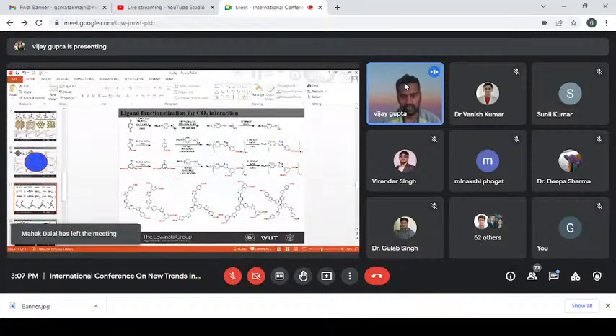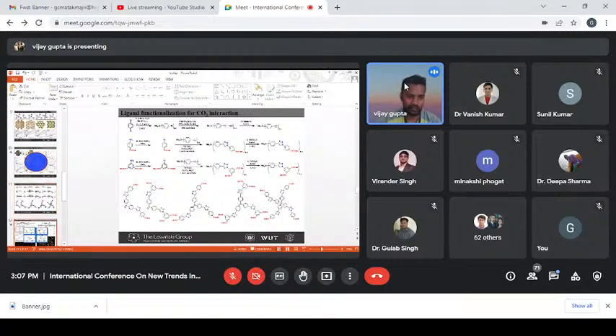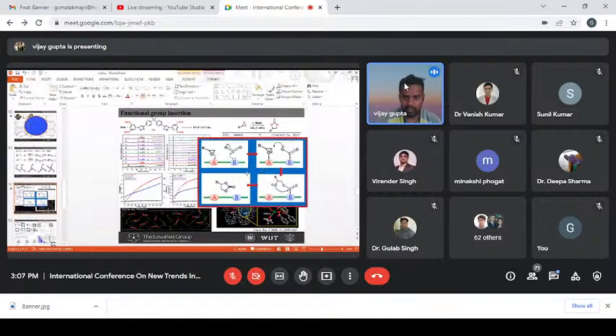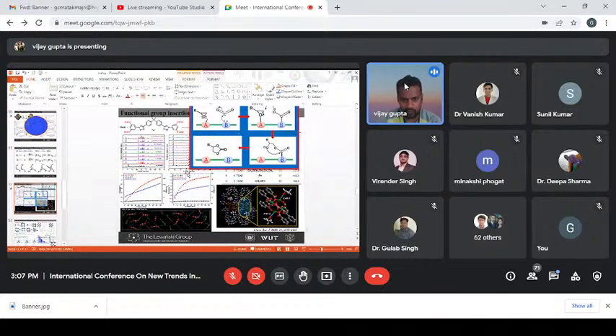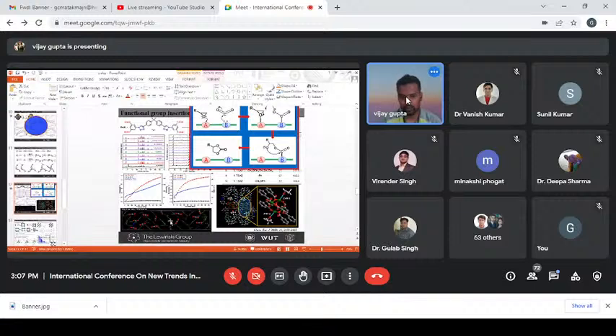And another strategy is, again, we have further functionalized our ligands with triazole functionality, because this is also known to interact with the CO2 molecule, and it will definitely help us to enhance the CO2 adsorption and selectivity. We can see from this slide that we have very high selectivity and very high CO2 adsorption values. In this case, we did some simulation studies also to show where the CO2 resides in the framework. Here we can see this CO2 interacts with these triazole units, and the active metal site, that is the unsaturated metal site, helps in this epoxide activation. This is the small molecule epoxide.